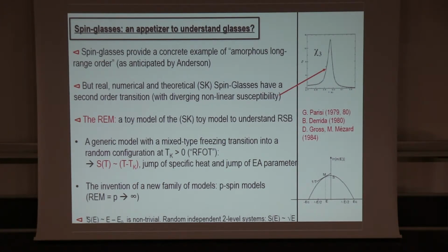And in particular, what's remarkable when you think about it from a naive point of view is that this transition to an amorphous order is accompanied by a divergence, and the divergence is the divergence of the nonlinear susceptibility. So these are experimental data by Laurent Lévy, I think, where you see that as you reach Tk, this third order susceptibility actually diverges.